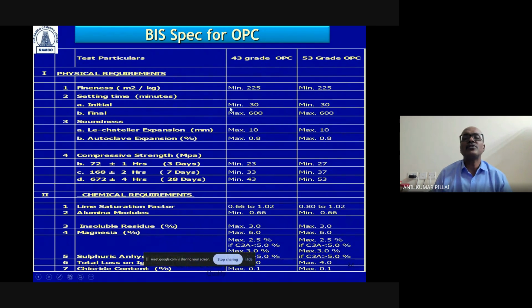Then you have the setting time. Of course, the BIS states between 30 and 600 minutes, so you can have a cement manufactured between these two limits. Normally you will find that the initial setting time of cement will range between 150 to 200 minutes, and final setting time somewhere around 180 to 300 minutes. Le Chatelier expansion and autoclave expansion are basically done to measure the soundness of cement, so that there is control over the expansion of the cement mortar. By Le Chatelier expansion, it should not exceed 10 mm.